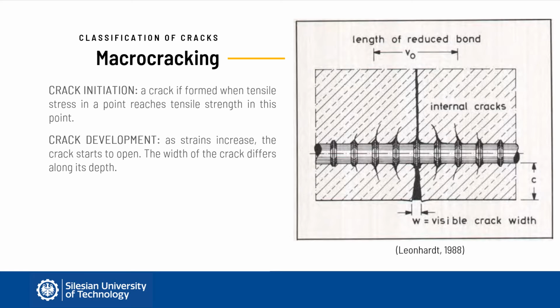Mind that the width of the crack differs along its depth. Especially, it may be different at the level of reinforcement and on the surface. This is important when the width of the crack is measured in an element. The on-site measurements usually provide the width of the crack measured on the surface, while in laboratory tests the measurement devices are often mounted on reinforcement and hence give the crack width in this location.